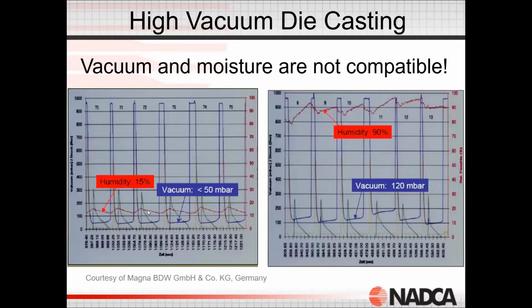This is once again a fingerprint. This is actually a snapshot of the vacuum system in operation. So here we're not only looking at the humidity level, we're looking at how well we're drawing a vacuum. So we turn the vacuum on, we draw the vacuum down, and we're achieving about 50 millibars in this particular die. And then each one of these is a shot, a die casting being made. So we're monitoring the vacuum level, and then we're also monitoring the humidity level.